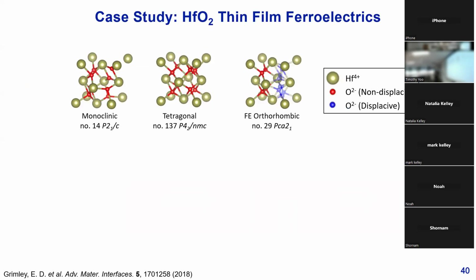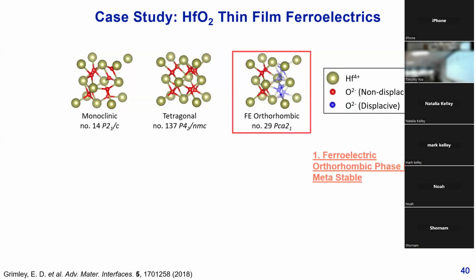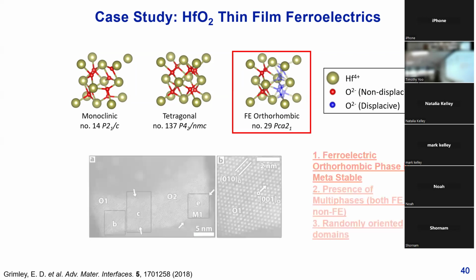And so for this, we're going to be using a very interesting case study of hafnium oxide thin film ferroelectrics. Why hafnium oxide is really cool for this particular case is that it can exhibit multiple different phases when grown. However, the only ferroelectric phase is actually this orthorhombic phase, which is metastable. And so far, single crystal orthorhombic hafnium oxide has not yet been achieved.